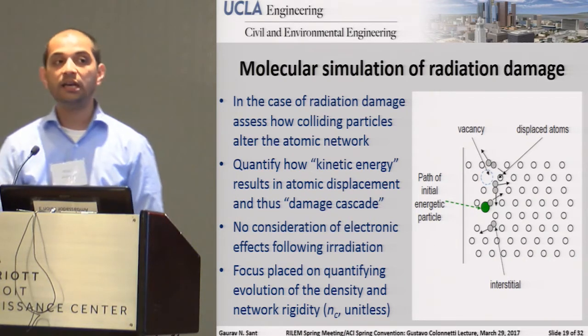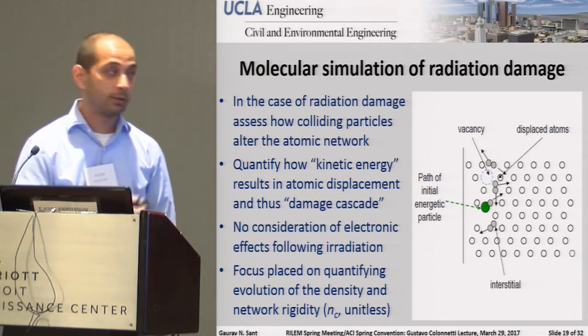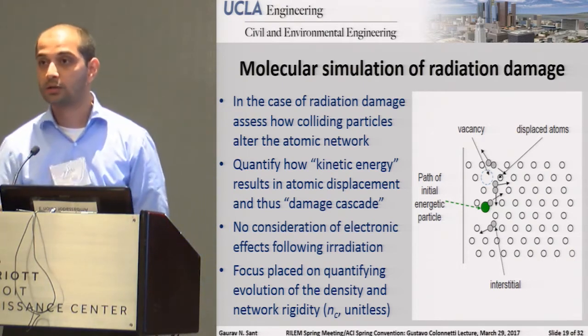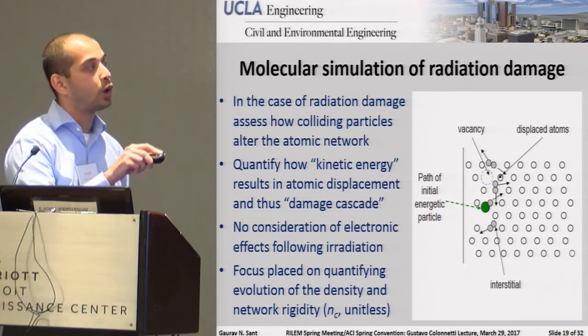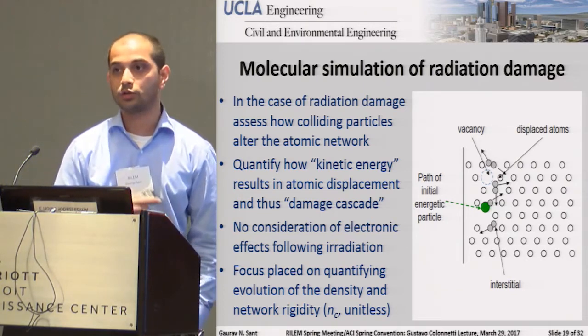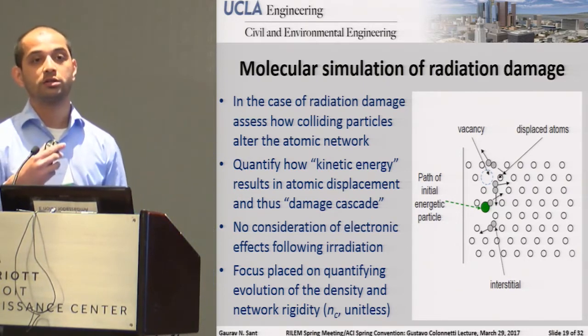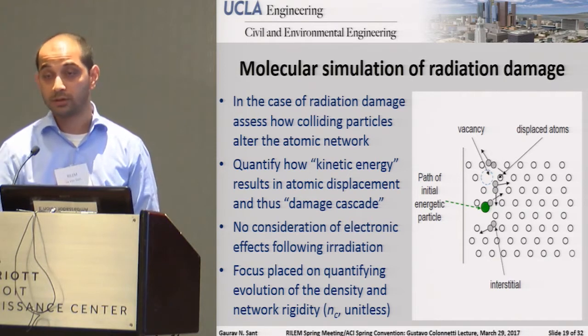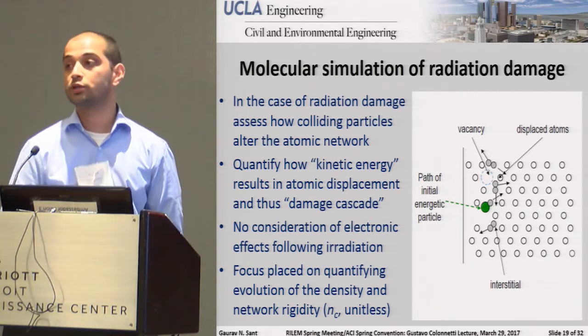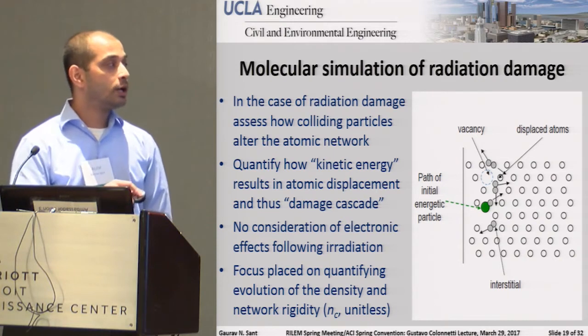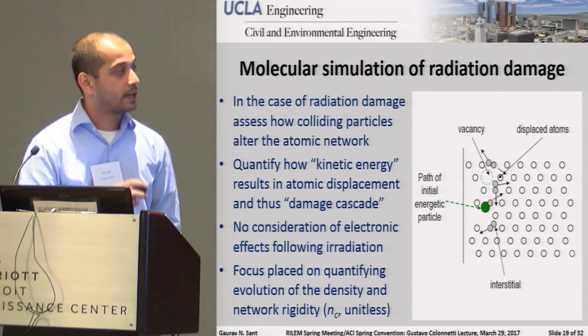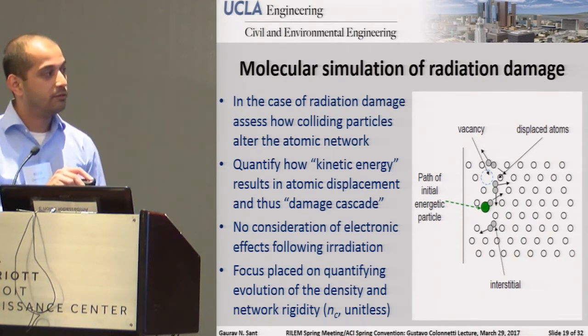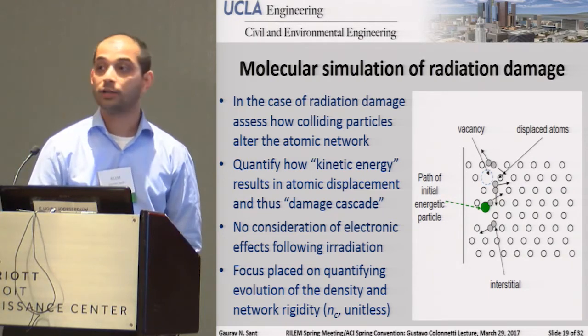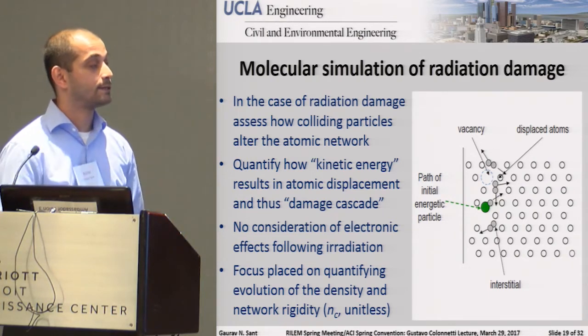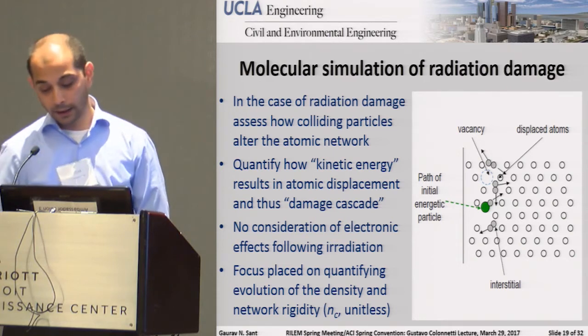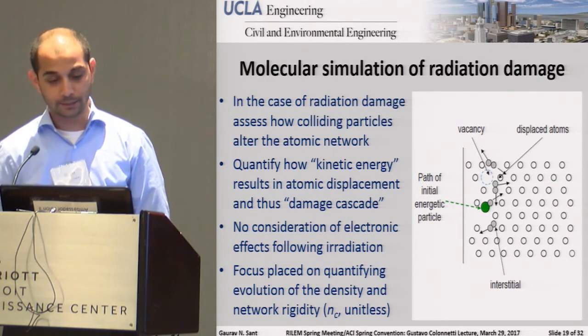Of course, this is really a billiards game, because even when we do this in molecular simulation, we do it using, for example, realistic coordinates and realistic positions. However, you do not consider any of the electronic effects that are associated with irradiation. So you do not consider, for example, any interactions with any of the atomic subatomic particles. You don't consider any interactions with the nucleus, as an example. So really what we were interested in doing, and I'll talk about this in a second, is quantifying, for example, first the evolution of the density, because you can imagine that these things are going to experience a reduction in density, and the network rigidity, which I'll talk about in just a second.